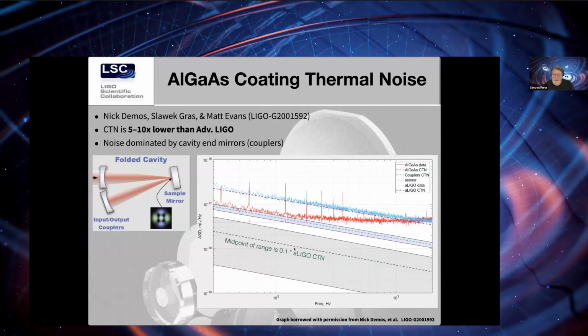And the reason that it's just an estimate is because the noise was dominated by the apparatus itself. Specifically for this folded cavity, you have the input and output coupling mirrors, and they have an amorphous coating, and the coating thermal noise in these coatings was actually the dominant source of noise. So in order to try and actually make a direct measurement of the coating thermal noise, we had to investigate getting new coupler mirrors, which we've now done.